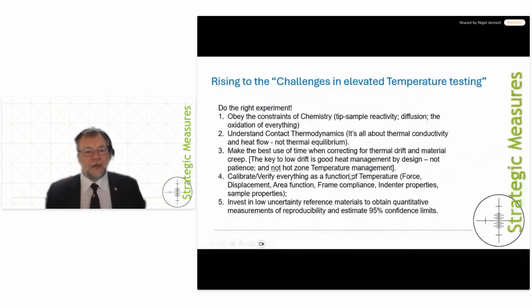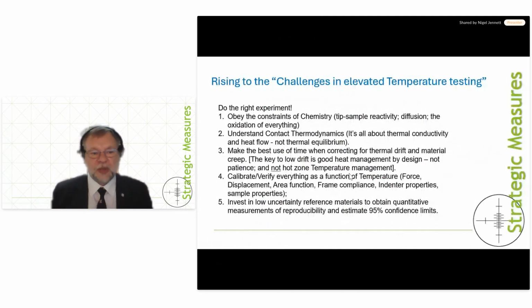So I've run over time, I do apologize. But what I'm trying to say is there are some challenges to instrumented indentation testing, and you can meet those challenges. Just do the right experiment, respect the laws of physics and chemistry, make the best use of your experimental time, and maybe do some elastic modulus corrections. Calibrate everything, even if you think they should be constant, as a function of temperature. And as soon as they come on the market, invest in low uncertainty reference materials so that you can check what you're doing.